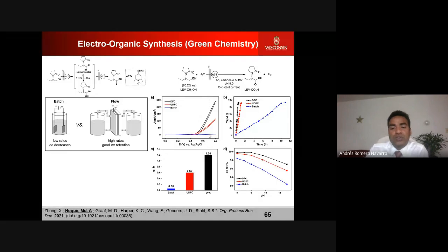So the blue one is showing the cyclic voltammetry we are carrying out in the batch under exactly identical conditions. The red one is showing when we are doing it in flow, in undivided flow. So what does it mean? In this flow cell, we have a cathode and anode, and in between, if there is no separation, then we call that an undivided flow cell. But if we put some divider, some membrane, then it is a divided cell. In the undivided cell, the red trace is showing that one.